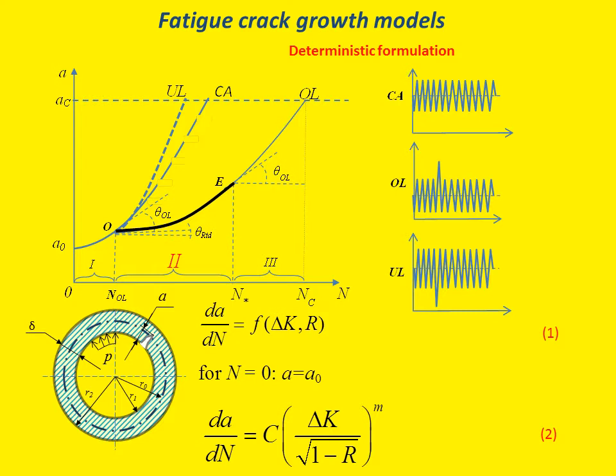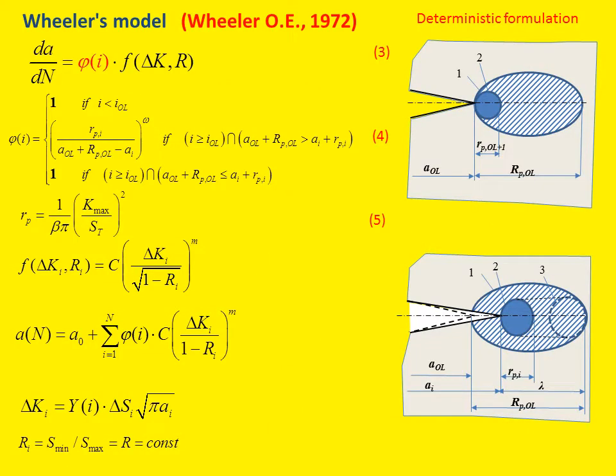Multiple experiments show a notable decrease in crack growth rate after the overload. This delay cannot be described by the Paris model that is commonly used to describe the kinetics of fatigue crack in the components subjected to constant amplitude loading. And Wheeler in 1972 proposed a simple model that allows describing this effect.